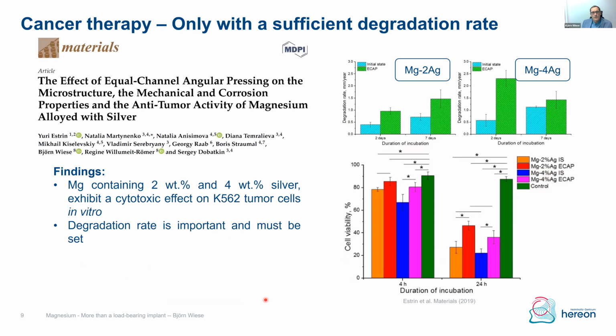The first work that was published out of it was on how to improve or change the mechanical properties, the microstructure, and the corrosion properties of as-extruded magnesium with 2 and 4 weight% silver. And the main impact for the treatment of cancer is that we now see an increased corrosion rate if we do this ECAP process on our as-extruded material.